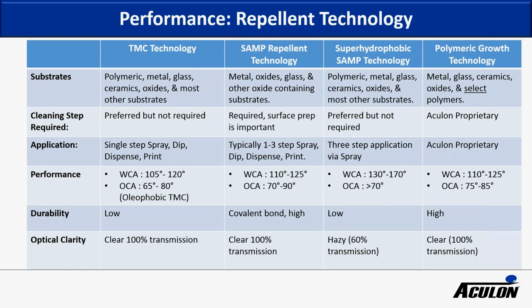Here's a table that compares our repellent technologies. Starting with the TMC technology, this is broadly applicable to not only metals and glass, but also polymers, ceramics, and most surfaces. It's fairly easy to apply, doesn't require extensive cleaning. It's usually a single step process, with usually pretty good performance. We are forming chemical bonds to the surface, but they're not quite as strong as a SAMP, so we've got to mark the durability as low. The thickness is usually between 2 and 10 nanometers, so it doesn't affect any optical properties of the substrate.